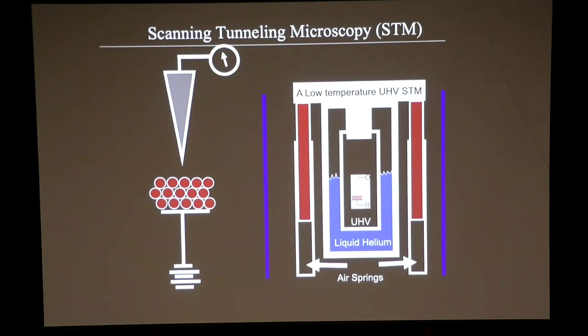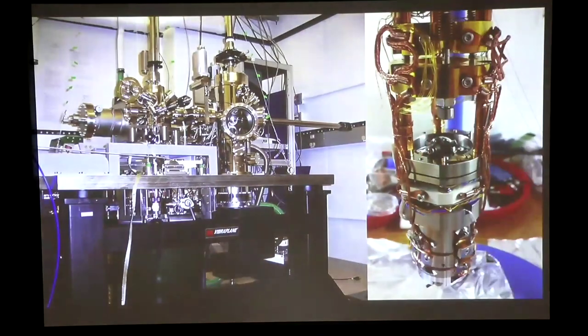So at the end of the day, even though the STM itself is a tiny little thing, it ends up that the machines that we call scanning tunneling microscopes are these gigantic objects with ultra high vacuum chambers, vibration isolation legs, a dewar to hold liquid helium that can go to 300 millikelvin or even to dilution fridge temperatures. And this is an example, a photograph of one of the STMs in my lab. And the size of this is about an inch by an inch and a half. So it's pretty tiny compared to the scale of this object, which is the size of a room.